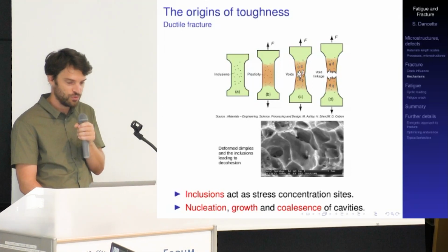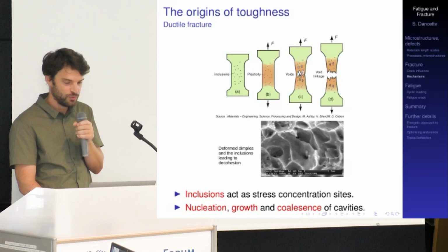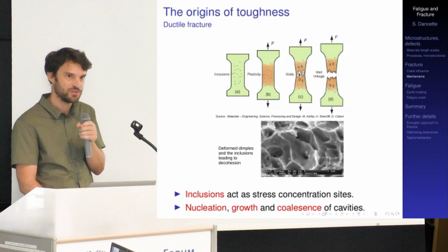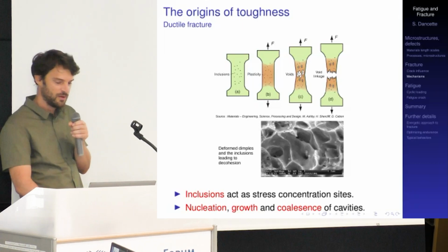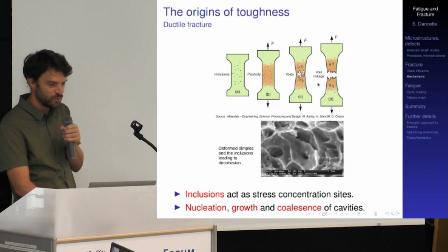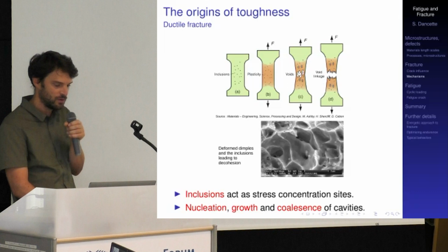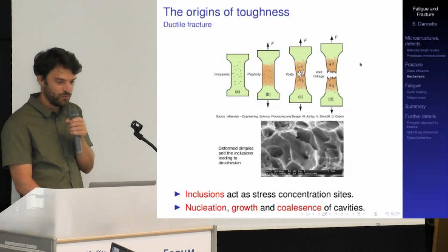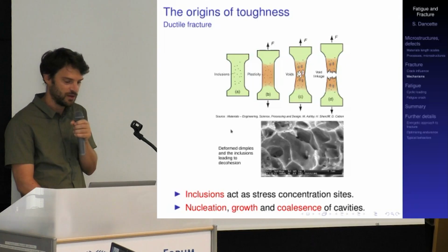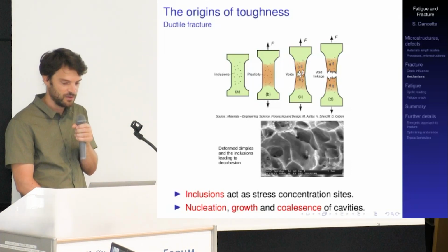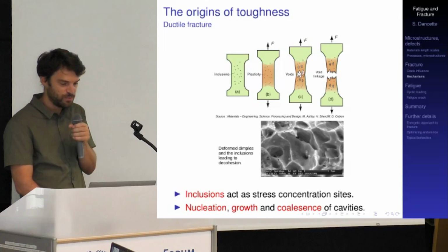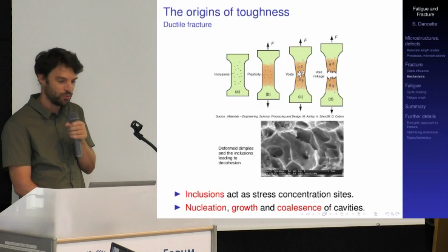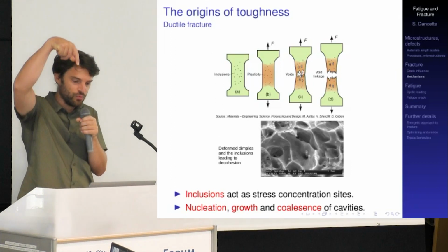When you continue loading the material, the voids will grow. At some point, they will grow so much that they start to coalesce, to bridge together. The final stage where the voids coalesce together is called coalescence, and this is what leads in the end to the final fracture of the material. When you look at such a metal, for example a mild steel fracture surface, in a scanning electron microscope, it is very probable that you will see dimples at the fracture surface. The dimples are these circular patterns, corresponding in fact to the voids that you look at from the top.